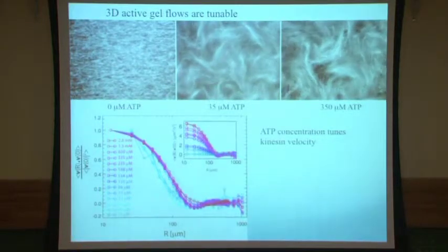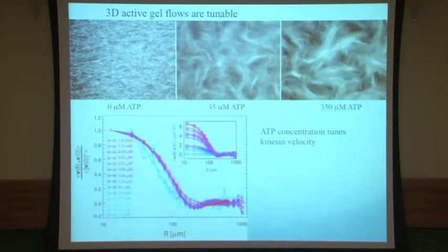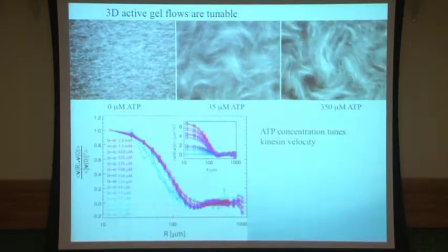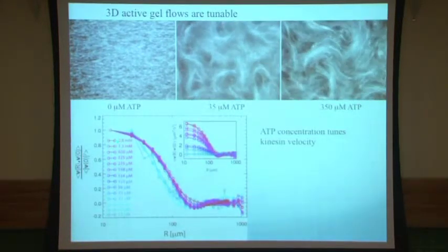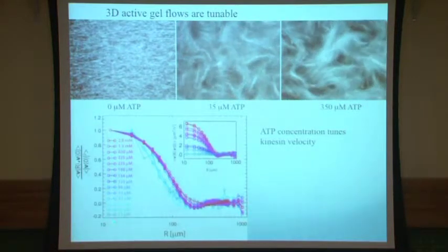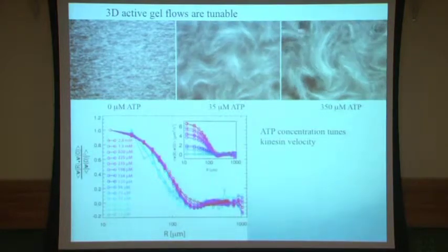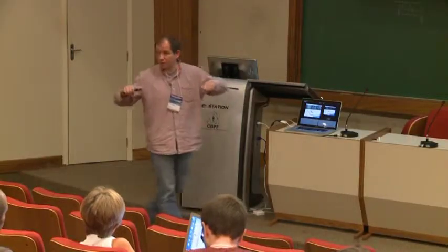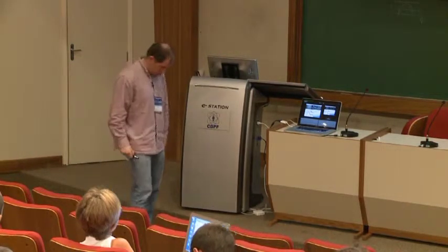It says that anything within 20 or 30 microns is essentially moving together, and then this correlation function drops down and becomes slightly anti-correlated, and things above a few hundred microns are anti-correlated. Things actually scale reasonably well at different ATP concentrations, so I can renormalize the speed, and there's a characteristic length scale of about 100 microns. We believe that this is essentially determined by the buckling length scale of a microtubule. Okay, so that's the length scale of, yes?